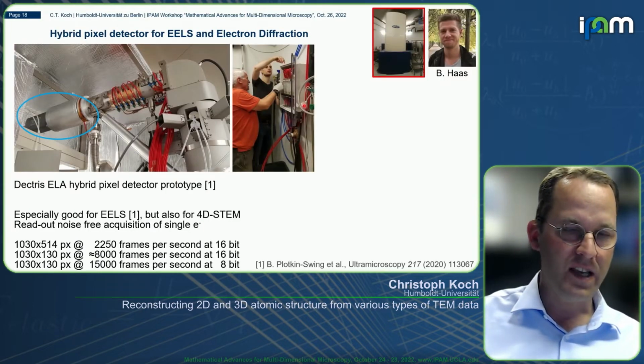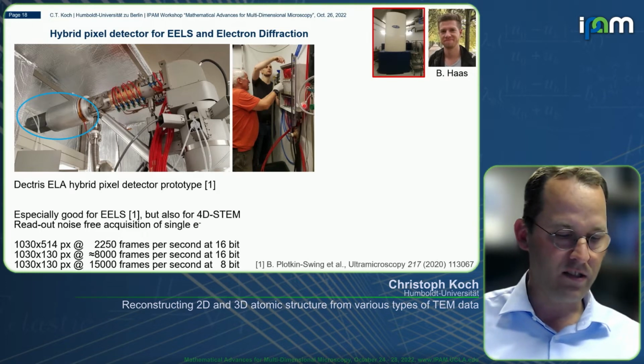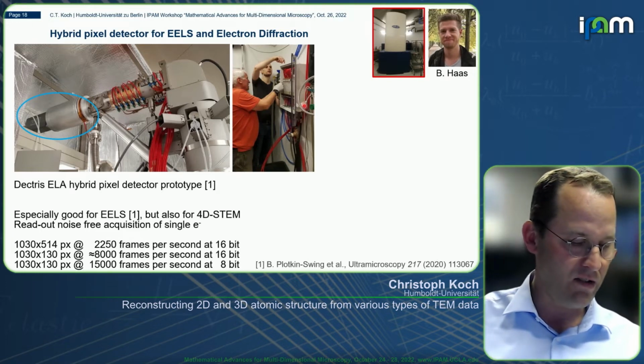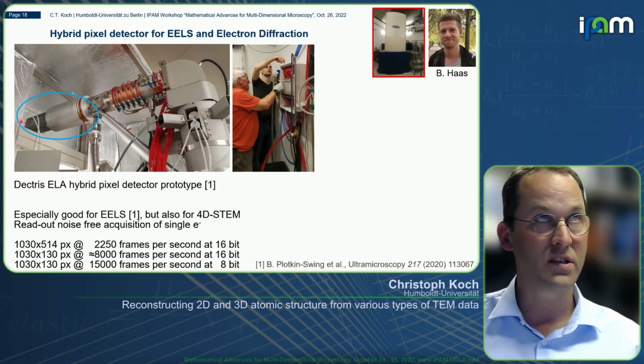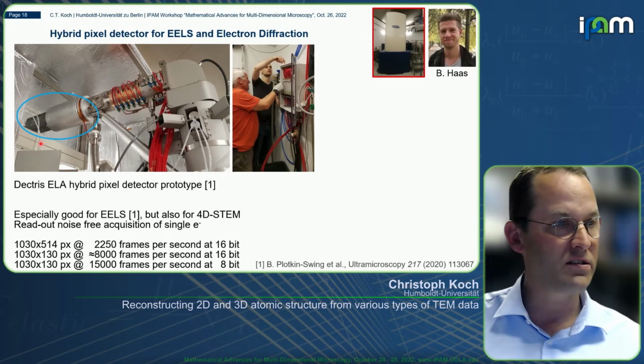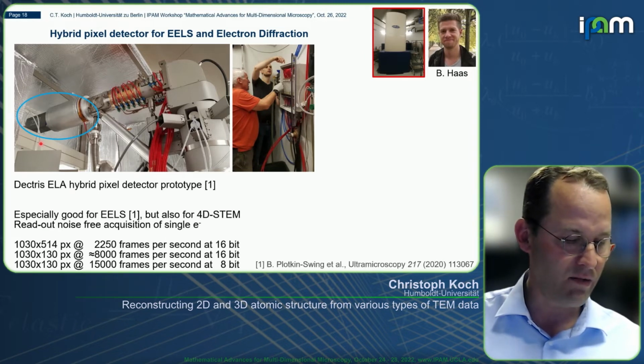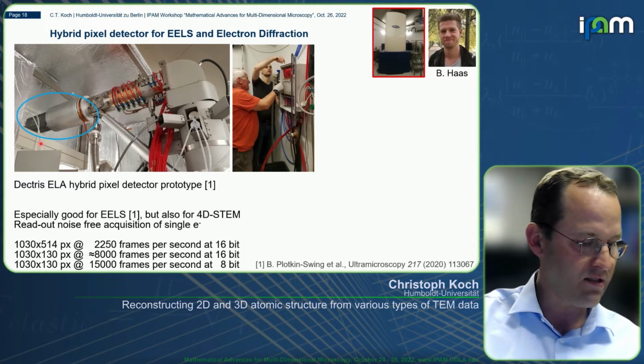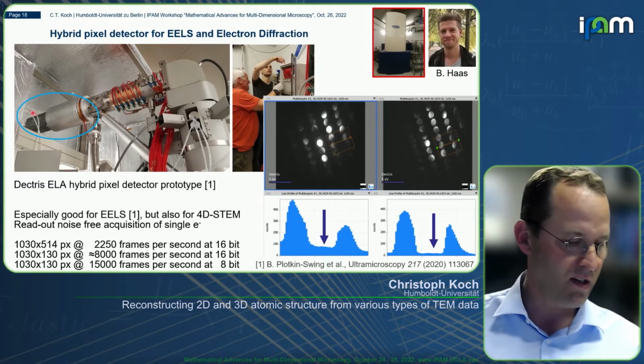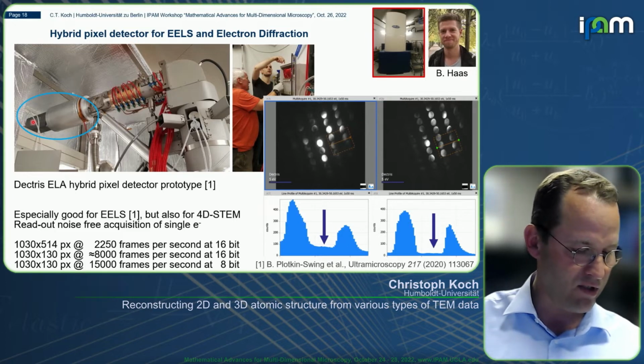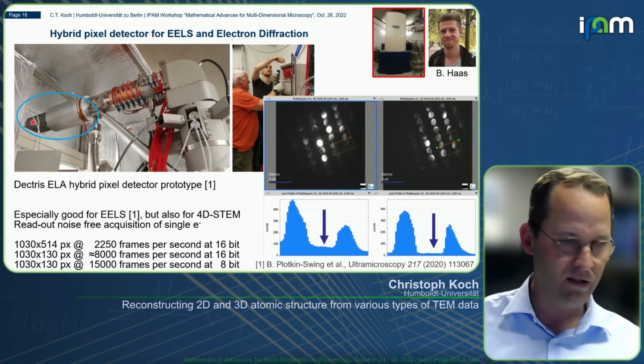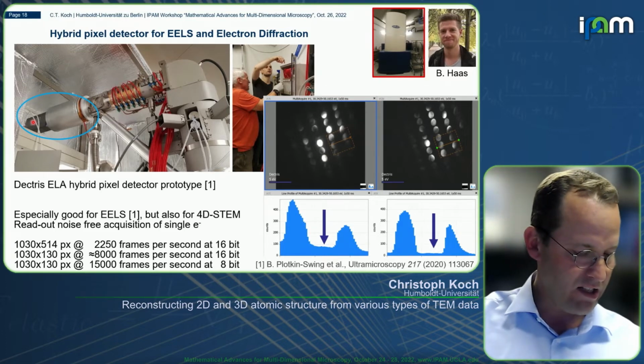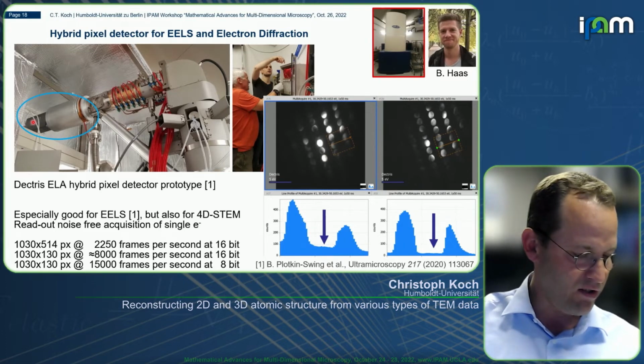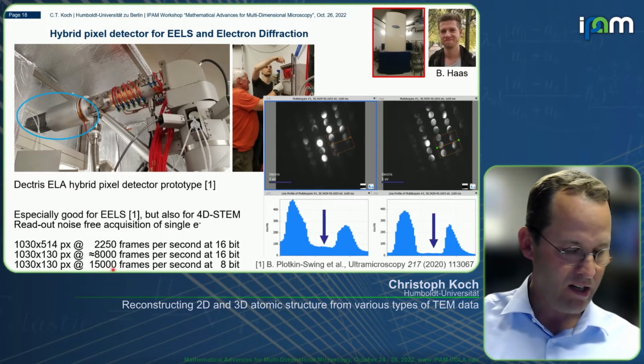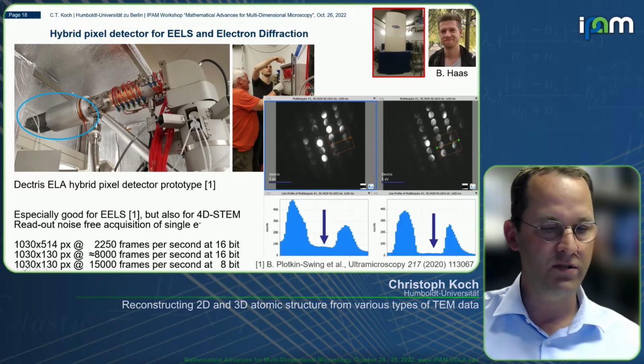But going now from this SEM to a 200 kV instrument, which can also go down to 30 kV. This is now a Nion HERMES, and shortly after we purchased this, which is now nearly 3 years ago, or well, that is at least when it arrived, we also bought one of these direct detectors for this instrument. It's now not a Medipix, but a Dectris ELA detector, which is also one of these hybrid pixel detectors, and it can go up to 15,000 frames per second if you reduce the size, the area that you read out, and also if you reduce the bit depth from 16-bit to 8-bit.